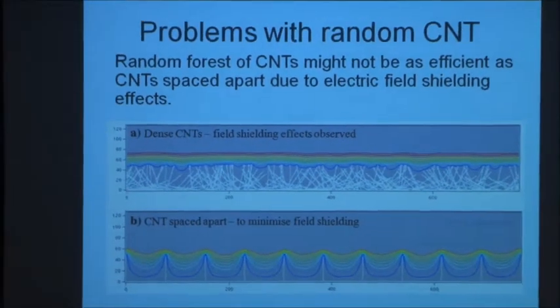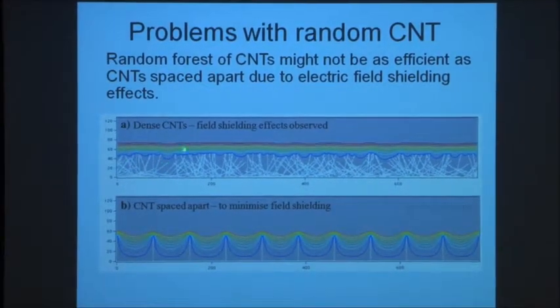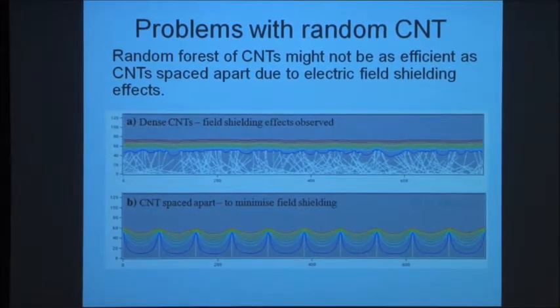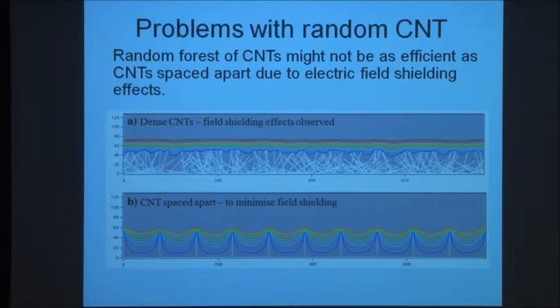When they're very close to each other, however, what you find is they shield each other. So if you apply a bias here, the field will focus on this one, but all the ones down here, when you've got the spaghetti field, the field doesn't penetrate them. And so the only ones that emit are the high ones, the tall ones. And you tend to find with spaghetti, only about 1 in 10, or maybe 1 in 10 of the CNTs actually emit.